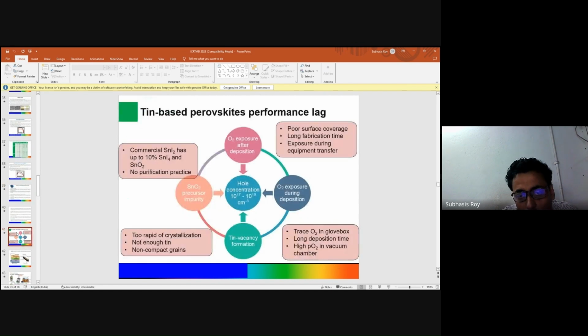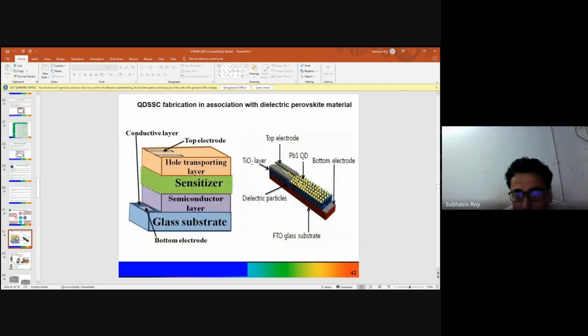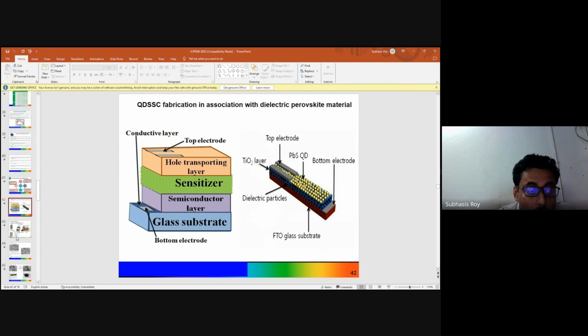Till now, some problems remain. Oxygen exposure is still a challenge. When it is open to the oxygen atmosphere, it degrades and the degraded properties increase. So we need to overcome these things. And also, we are putting different types of dielectric material in the solar cells as a capping agent, so that the lead iodide does not come out of the systems, and it gives much more stable solar cells.